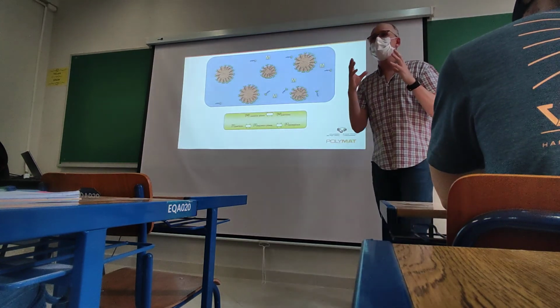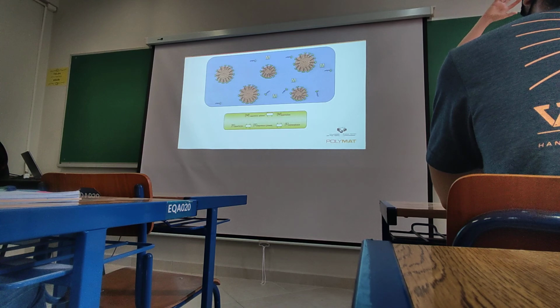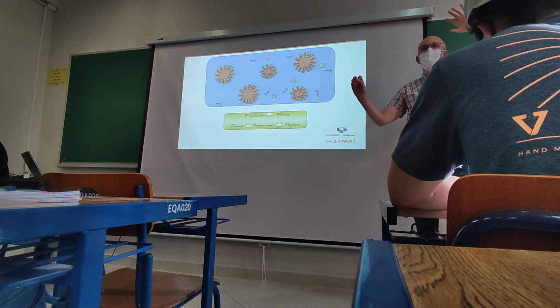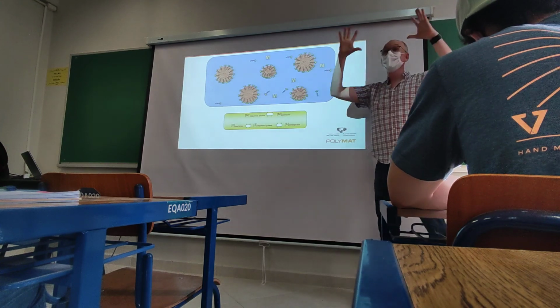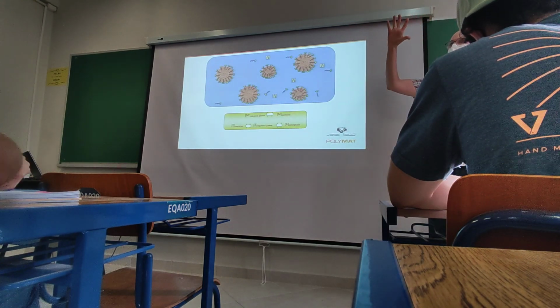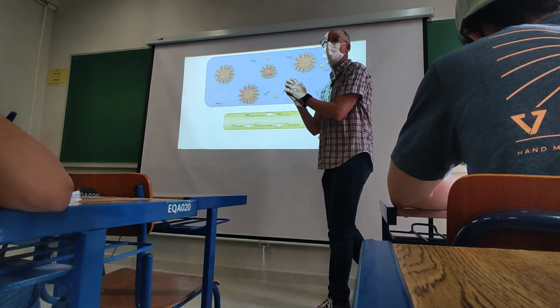One thing that is important, for instance, to distinguish emulsion polymerization from suspension polymerization is that in suspension polymerization, the particles are formed in the droplets. You have big droplets, but the initiator is oil soluble, so you nucleate the droplets. In emulsion polymerization, you don't nucleate the big droplets, you nucleate in micelles. So the size of the particles is much smaller in emulsion polymerization than in suspension polymerization. In suspension polymerization, the size of the particles is micron size or even millimeters in some cases. Here we are dealing with nanometer scale polymer particles.